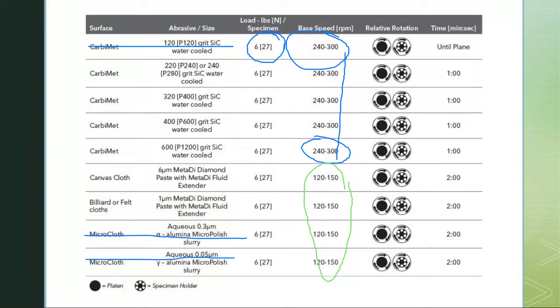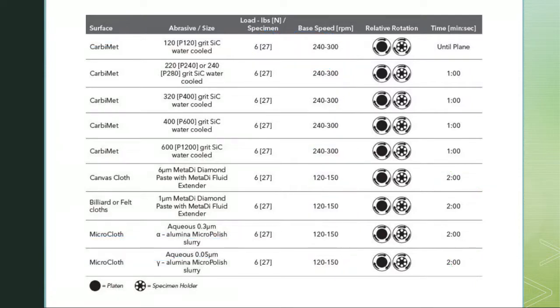And that goes into not wanting to create anomalies on your final polishing surface. So you decrease the base speed and you increase the time at which you're polishing your sample. This prevents your carbide pullout, your grain pullout, inclusion pullout, disturbed metal on soft materials. This prevents edge retention issues because your mounting material is softer than your metal that you're polishing. So this is the reason why you decrease the speed, is to help prevent those unwanted anomalies that you would get on your final sample.